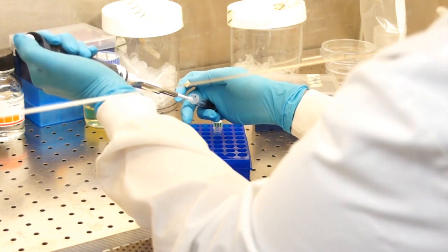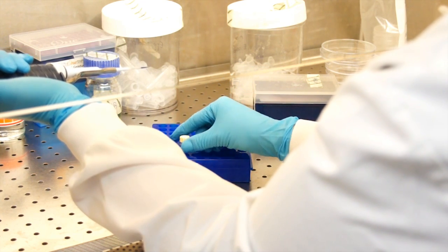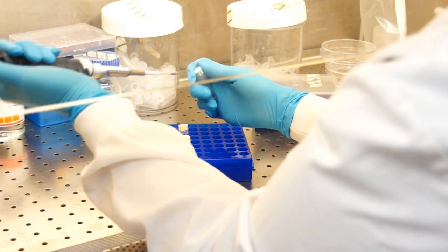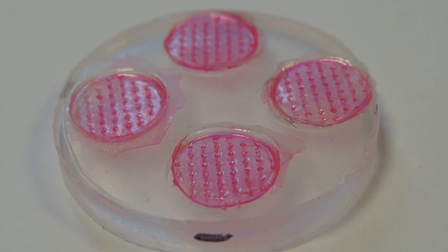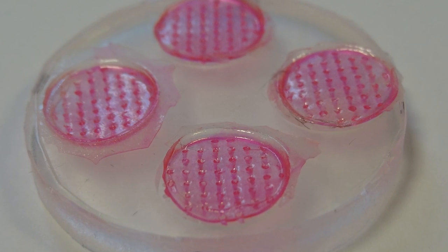The first step was critical: to see whether we could actually stabilise a live vaccine based on a recombinant virus. The next step was to see whether we could incorporate this stabilised vaccine formulation into a silicone template — the template has rows, or what we call arrays, of little cone-like needle shapes — and dry the vaccine in these little cones.